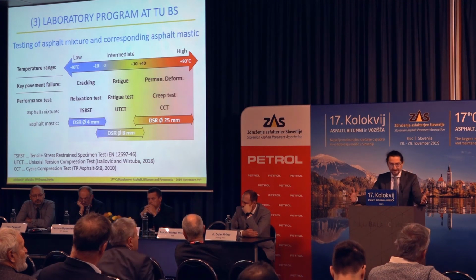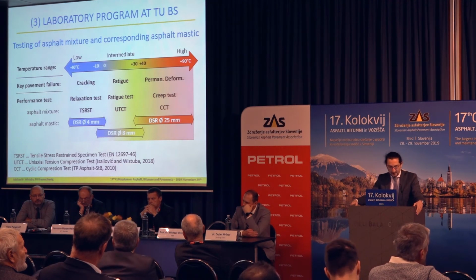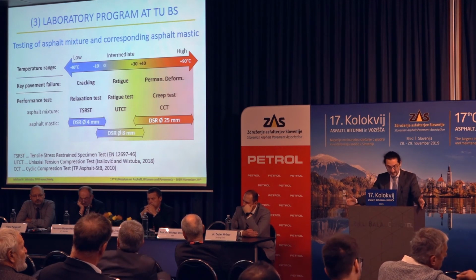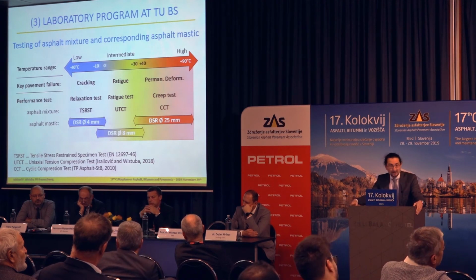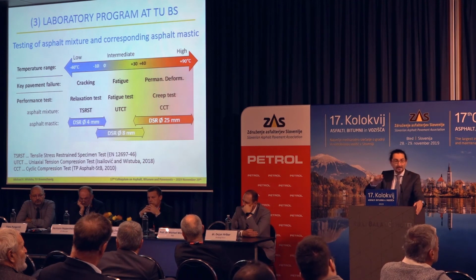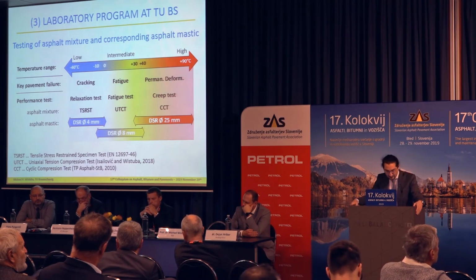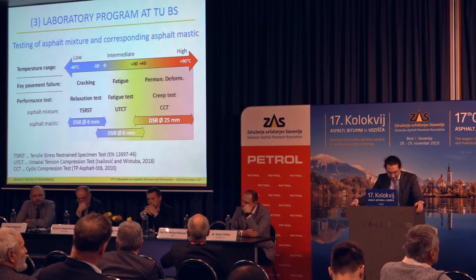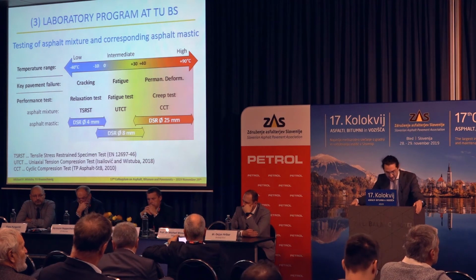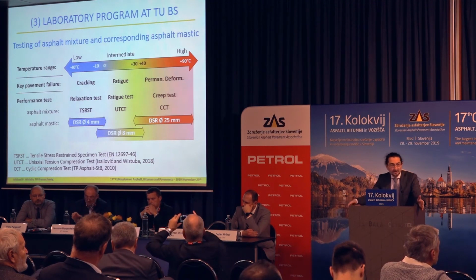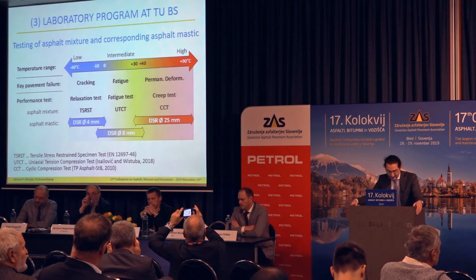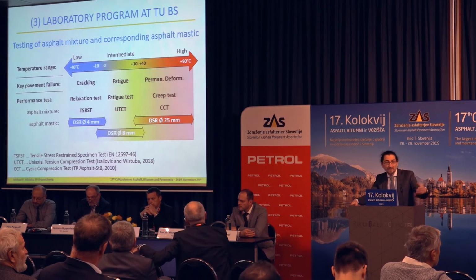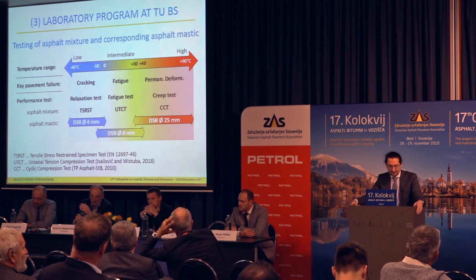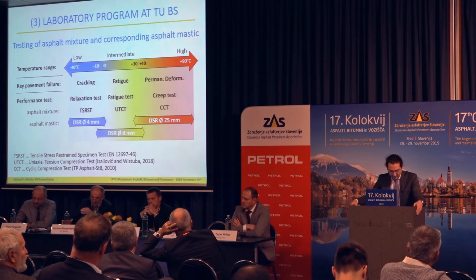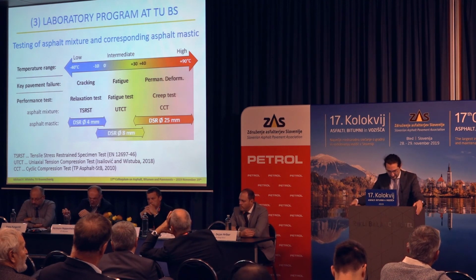And this is more or less the scheme of our work, that we looked at different temperature ranges and then at key performance parameters like cracking, fatigue, and permanent deformation. We selected performance tests at the asphalt mix scale, which was the tensile stress restraint specimen test in the low temperature area, then the uniaxial tension compression test in the moderate temperature range, and the cyclic compression test in the high temperature range. So we picked up known test procedures. They are nothing new. You can use them. They are all to be found in European or German standards.